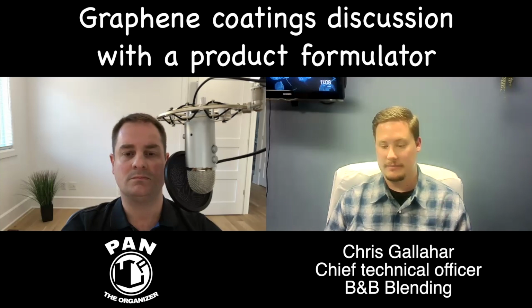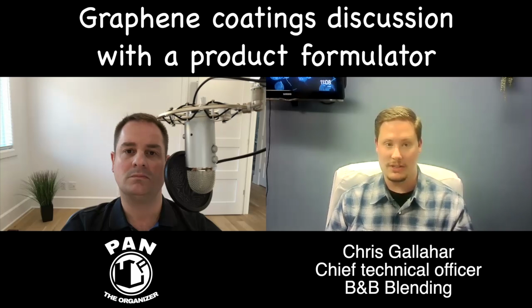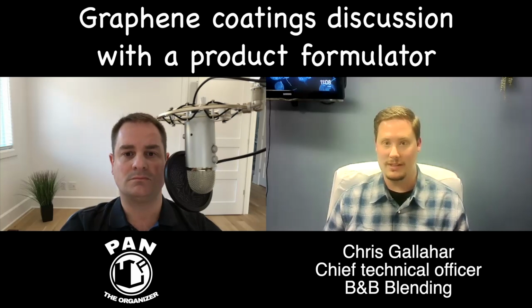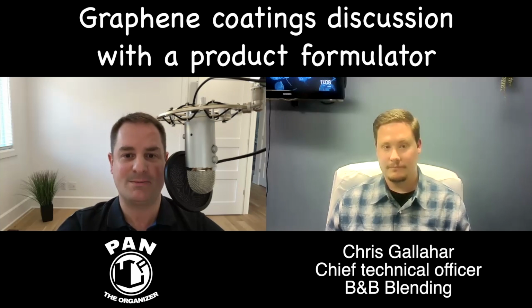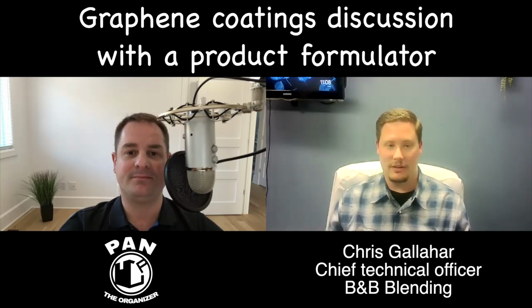And it's the same thing you see in some of these videos, where sometimes we watch a coating fail. And the reality is I know what's in that degreaser. It's probably actually reacting with the coating to bond to it and creating a surfactant film that's flattening the water. And everyone's like, well, that coating's out of the running. I'm like, it's actually probably still there. So it created some sort of residue on top of the coating that's masking its properties, right? Yep. And then people take a wet rag and they're like, see, it doesn't come off. I'm like, the wet rag's not going to cut it.